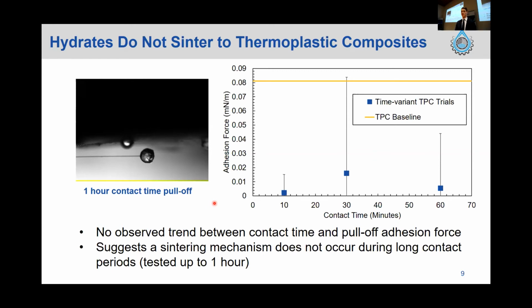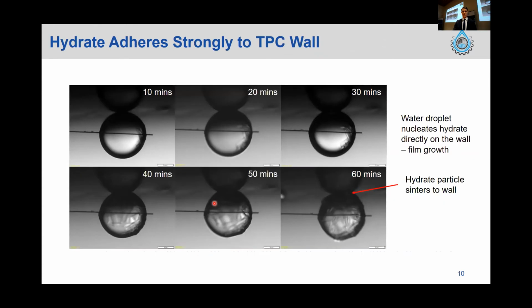So the next progression for this was to look at what might potentially happen if the hydrate particles nucleated on the wall as opposed to in the bulk fluid. So here is a figure, from left to right, showing the 10-minute intervals of a 60-minute annealing period for one of these hydrate particles nucleating on the wall. So basically the procedure for this was just that when the hydrate particle began to nucleate, it was brought into contact with the wall so that that nucleation mechanism could interact with the wall.